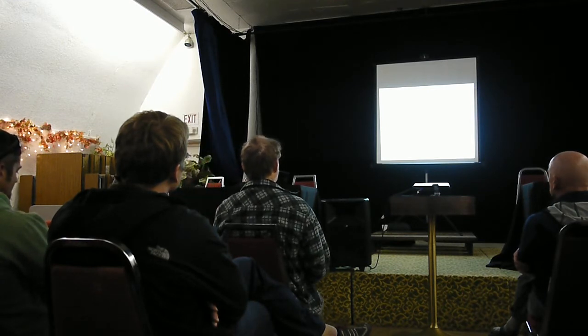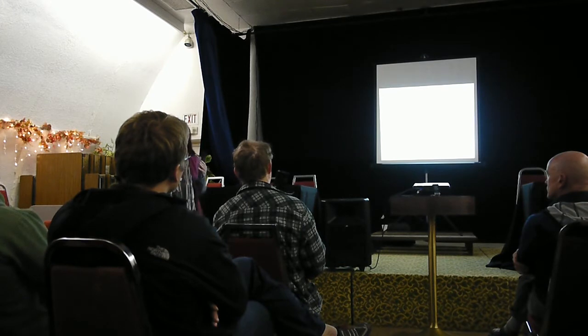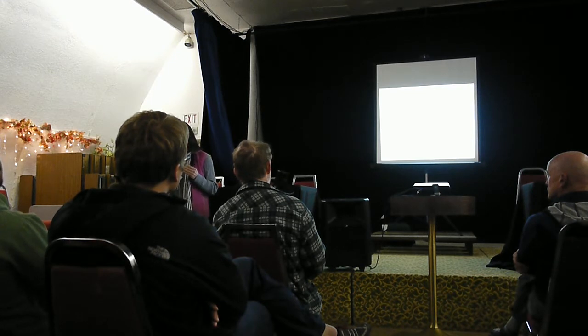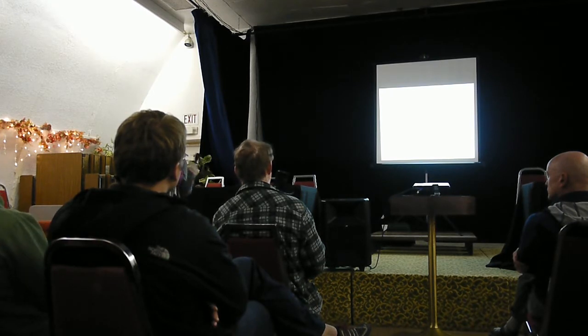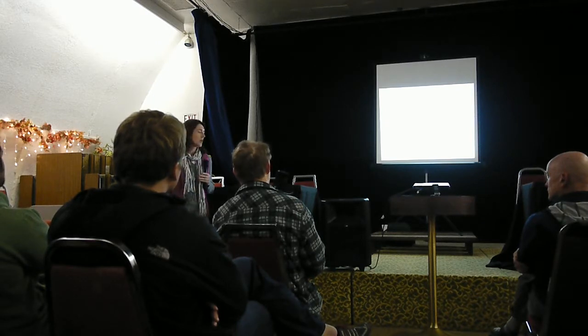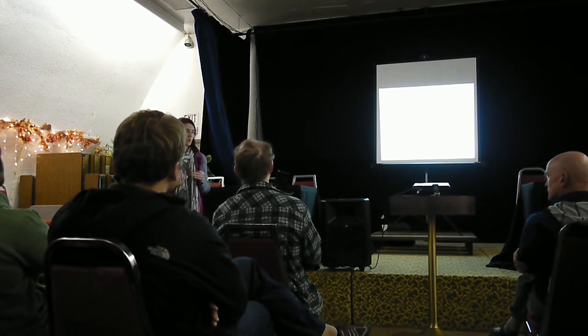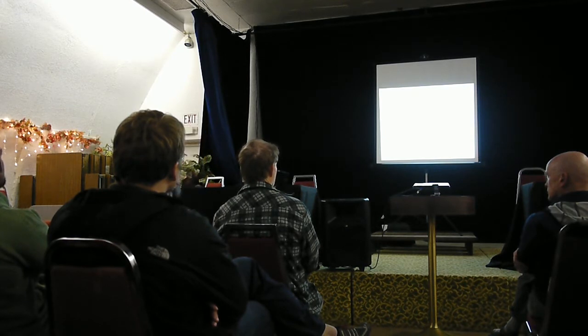Then there's galvanic corrosion. Galvanic corrosion is when you pair two dissimilar metals and give them an electrolyte, or water with something dissolved in it. It could be salts, or the organic acids you get from nature, any of those things. When you do that, one metal becomes the cathode and one becomes the anode. The anode is going to oxidize, and you basically create a driving force. You are going to drive corrosion in one of the two metals, the one that is less noble, the one that is active. The noble one will not corrode. So you have all these galvanic pairs, and when you pair them and give them an electrolyte, you'll have a galvanic reaction, or galvanic corrosion.